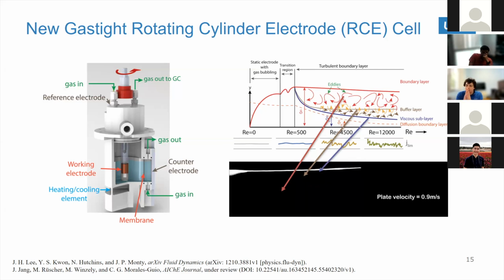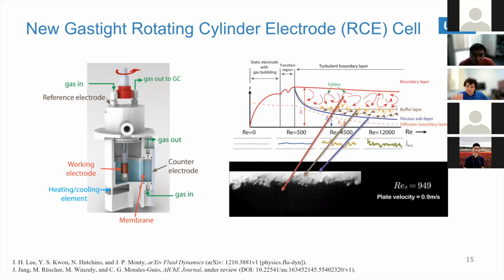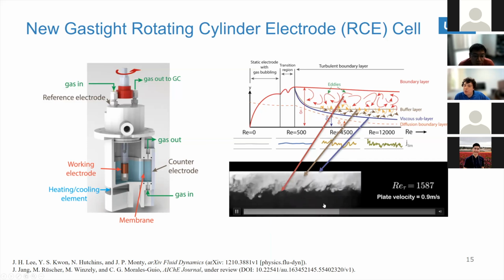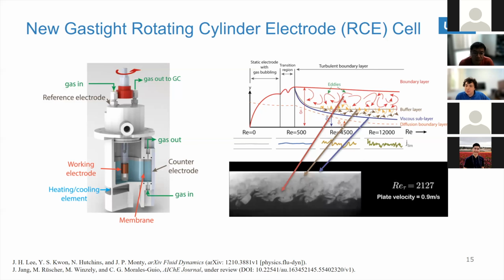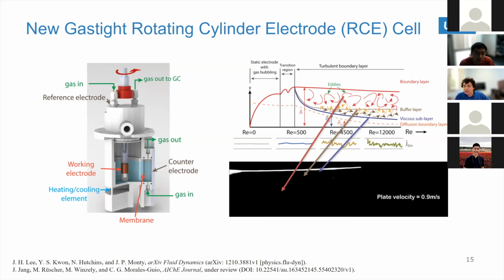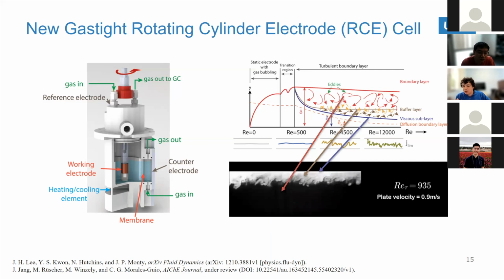Because near the surface of the electrode, the liquid is very, very static. As you go a little bit out from the electrode, you have the convection. In the cells that most electrochemists use, because we bubble some gas or we have some stirring, we're creating convection in the bulk of the electrochemical cell. We cannot visually see it, but near the surface of the electrode, this is actually what is happening.